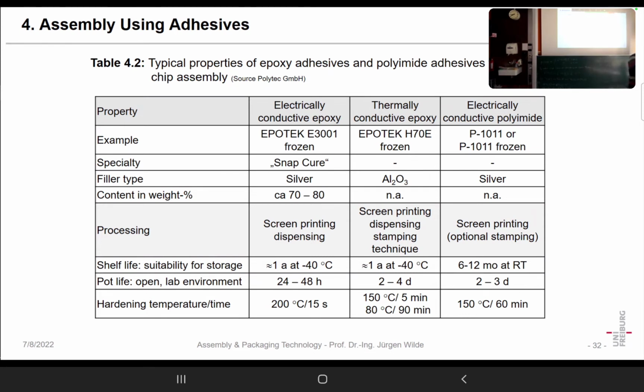You can put a hardener in a micro capsule of a third material, and that catches that hardener and keeps it from reacting. But going above that snap cure temperature, just the shield around the hardener is destroyed or dissolved, and then suddenly the reaction starts. So that's a good trick, but not all adhesives are snap cure.